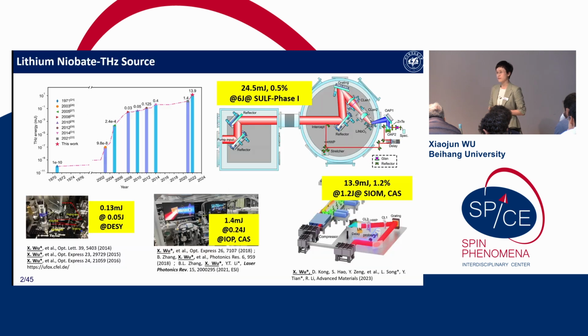Since Tom has already given a lot of introduction about terahertz importance, I will go directly to the terahertz source. Previously, in the last 10 years, what we have done is to build strong field terahertz based on lithium niobate crystals. We have tried our best to use femtosecond laser pulses interacting with lithium niobate crystal, and pushed the terahertz single pulse energy from the microjoule to millijoule, and then to tens of millijoule. Recently, we collaborated with SIOM, CAS using the petawatt SULF laser facility, and we got more than 20 millijoule terahertz out.